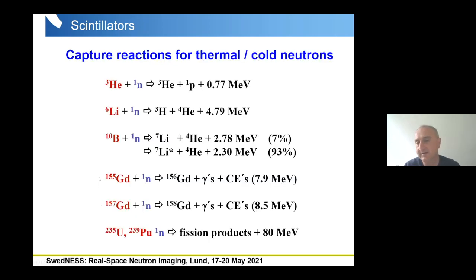So here you can see some nuclear reactions which we are using for producing this secondary radiation for the scintillation. The main reactions which we are implementing in our scintillating screens are the absorption of a neutron by lithium-6, where we have production of an alpha particle and a triton. And this triton is actually used for the scintillation. The alpha particles also produce a scintillating effect, but the mean free path of the triton is much bigger, and this is the limitation for the resolution.